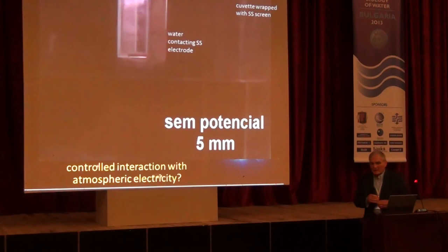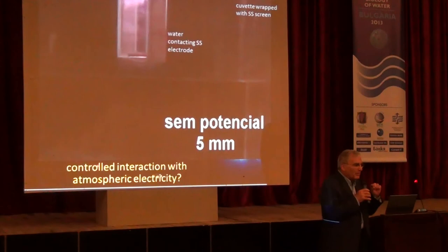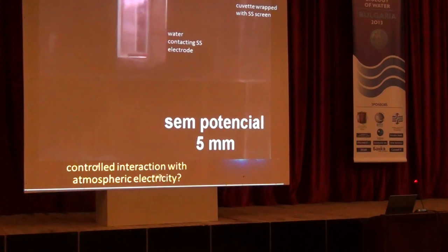If the metals are grounded, depending on the thickness of the oxide layer, you can still see a lot of potential gradient. You cannot go to very high potential, but I say very high is many volts. I think the maximum that you observe is in the range of 1 volt. Take aluminum, for instance. You may have a very thin aluminum oxide layer, but that's a very good insulator. So actually, you can build up charge on top of it, even on grounded metal.